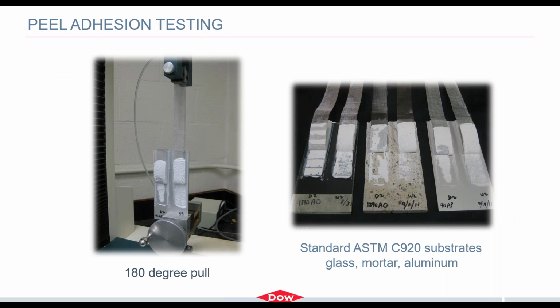They get extended at plus or minus 25. So another critical C920 test is peel adhesion, where we do a 180-degree pull, and this is done on 3 substrates, including glass, mortar, and aluminum, but we also do other substrates as well if the application is a different application or if the customer requests it.